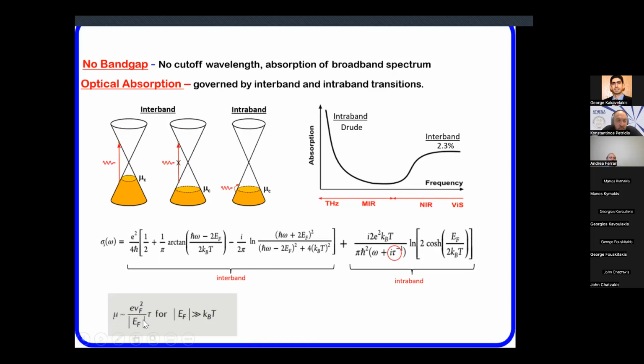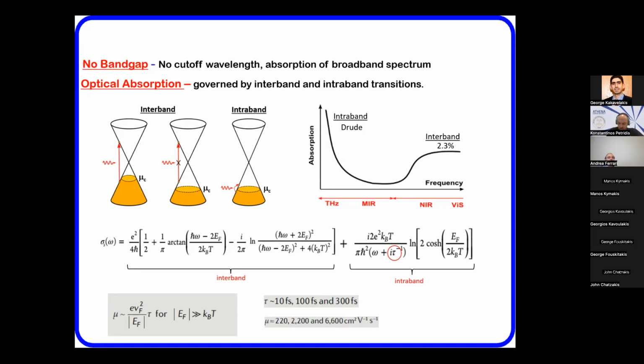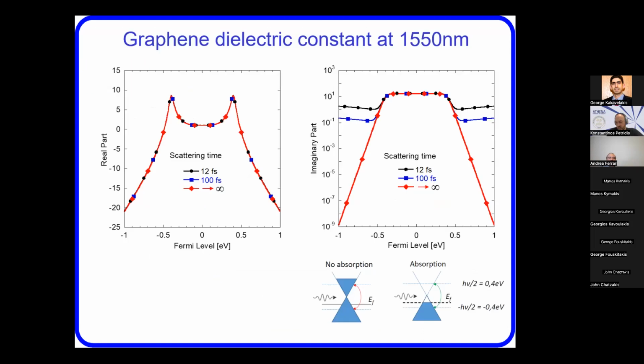So the mobility is related to the scattering time and to the Fermi level by this very simple formula, which basically tells you that a scattering time of 10, 100, 300 femtoseconds corresponds to a mobility of 200, 2000, 6000, okay? So these are sort of basic principles to judge how good a piece of graphene is. 200 mobility or 10 femtoseconds is a crappy piece of graphene. 2000 mobility, 100 femtoseconds, is a normal piece of graphene. 6000 or above is a very good piece of graphene, and is what people are trying to do now, not at 0 Kelvin, at room temperature over a large area.